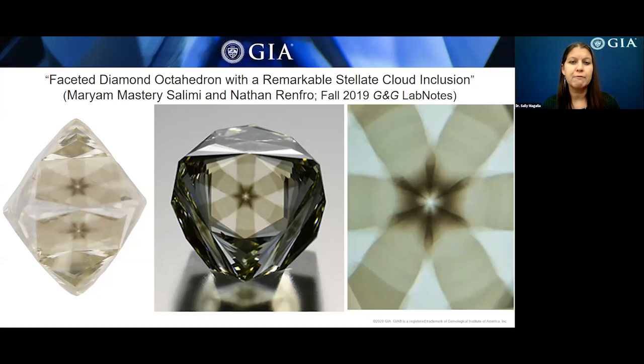This 3.7 carat faceted fancy brownish greenish yellow diamond was submitted to the Carlsbad Laboratory for Color Origin and Identification Service. This diamond was remarkable with its eye visible stellate cloud inclusion that consists of 6 legs adjoined at the center of that polished octahedron. Gemological examination revealed that it was a type 1A diamond, showing a typical Cape series in the visible spectrum. Hydrogen bands in the infrared spectrum and then the UV-vis absorption spectrum were consistent with what we see in hydrogen cloud inclusions. These clouds in diamonds consist of a high density of light scattering micro inclusions, and oftentimes they include high amounts of hydrogen, nickel, and oftentimes graphite as well.